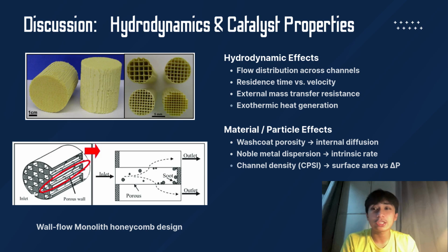This design provides a large surface area for reaction while maintaining relatively low pressure drop. Uniform flow distribution through these channels is critical. If the exhaust flow is uneven, some channels receive more gas than others, which reduces the overall catalytic conversion efficiency. There is also a trade-off between gas velocity and residence time. Higher velocity improves external mass transfer to the catalyst surface, but it decreases the time the gases stay in contact